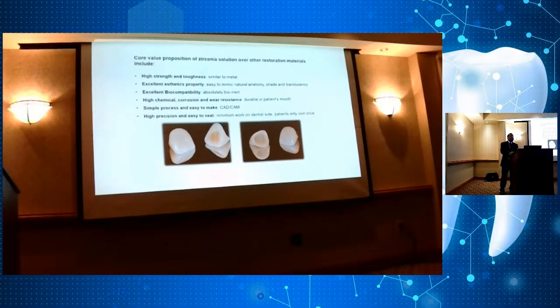The only way to treat this material after you've ground it a lot is to resinter it. In other words, you have to put it back into the ceramic oven. This is the last process you do. You glaze it, obviously. Put it back into the oven prior to the glaze, raise the temperature to 1,000 degrees and hold it in air. What this does is it actually seals these flaws. Okay? And then you can glaze it back and send it to the dentist.